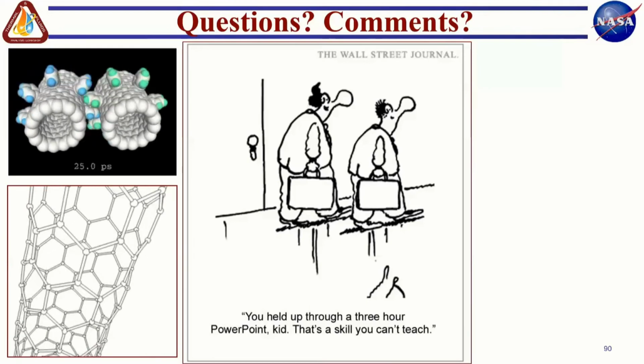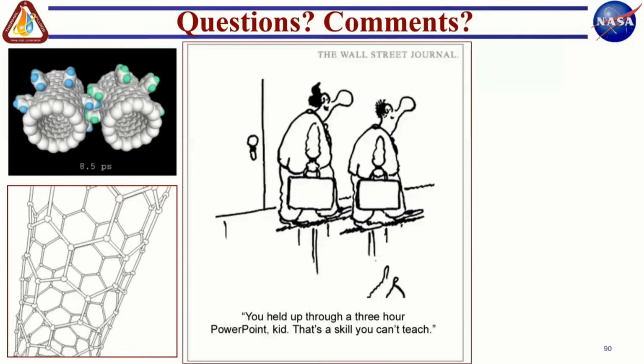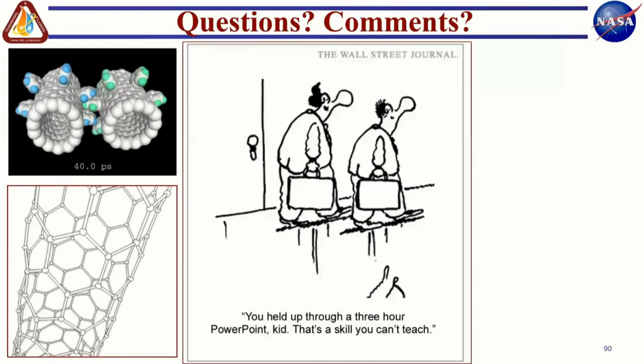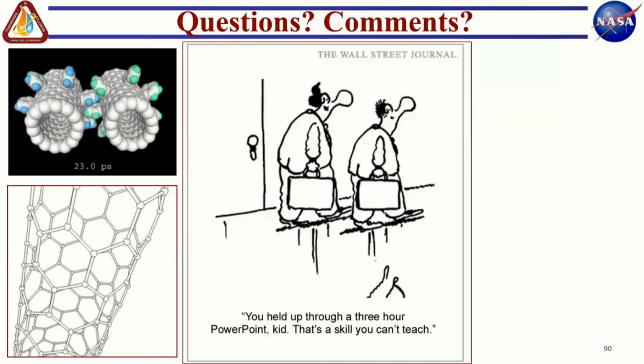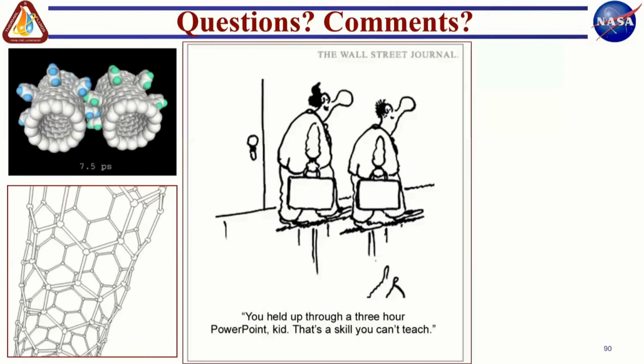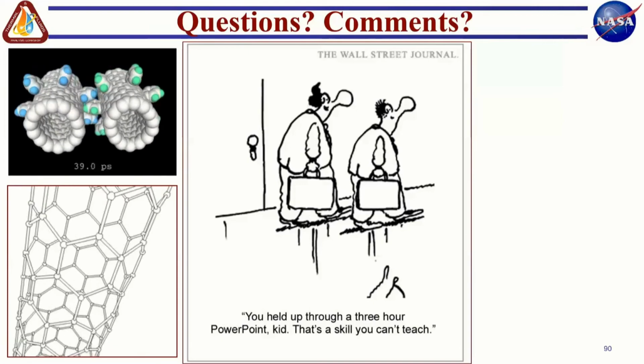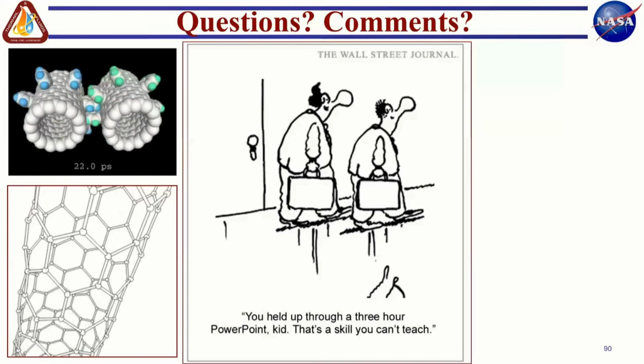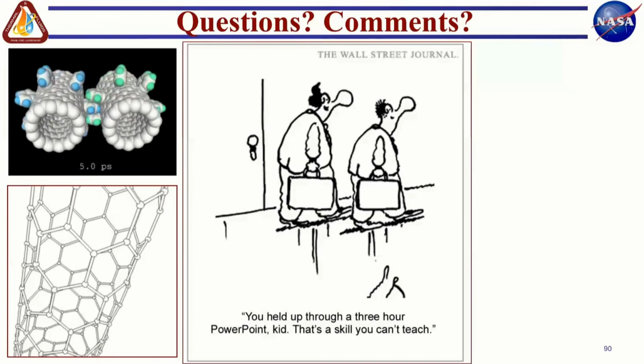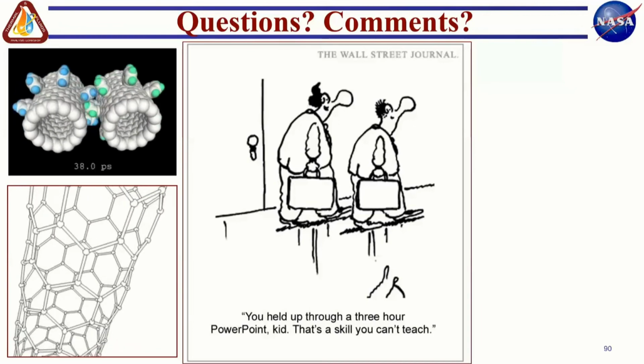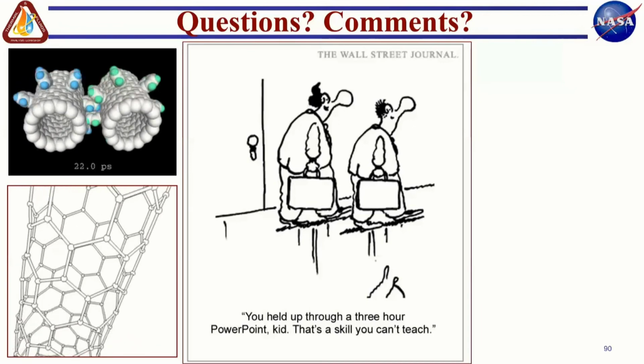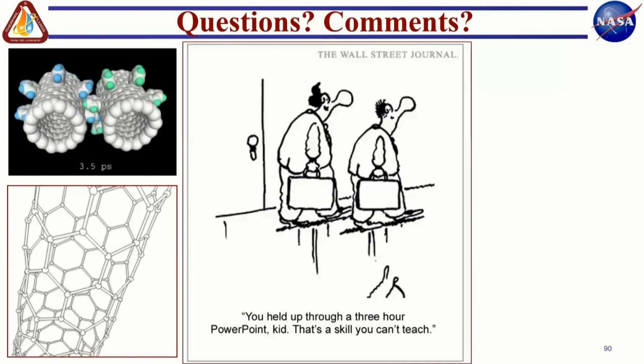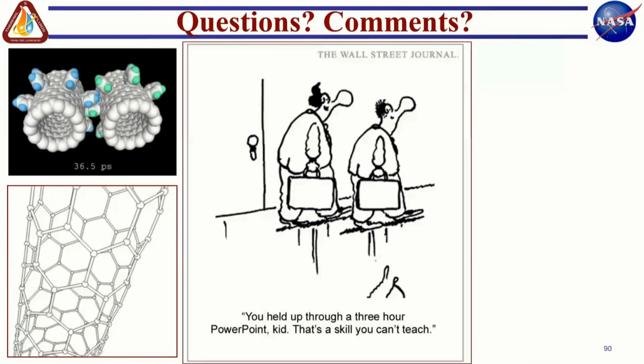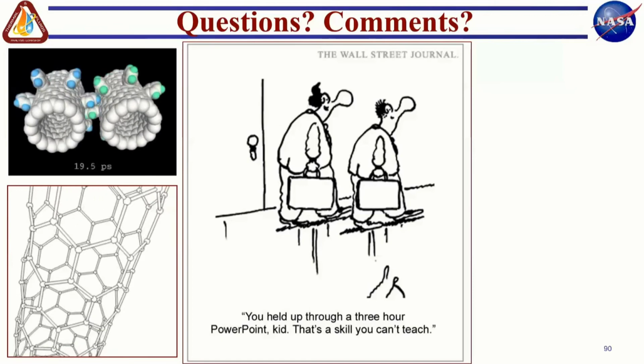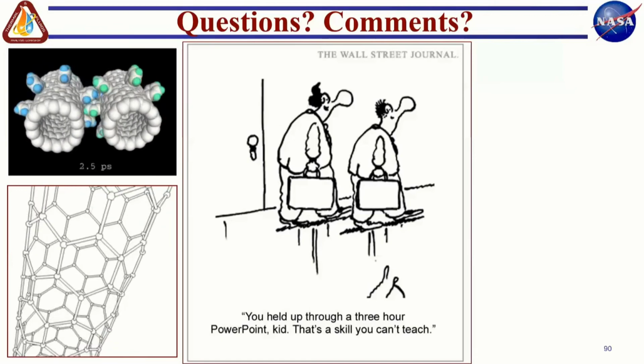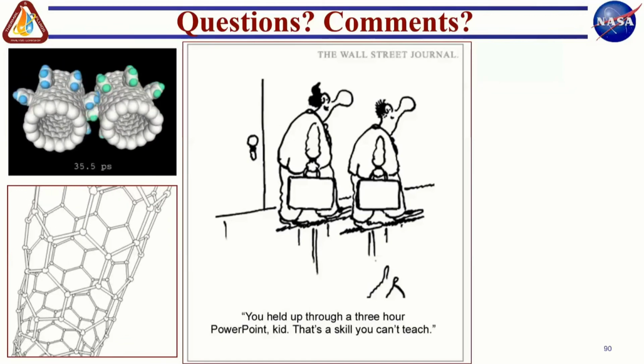bulk. And similarly, if there are other ions, so let's say you have put some sodium chloride as an impurity in the water, the carbon nanotube might like the sodium ions more than the chloride ions. And so you would also set up a concentration gradient for the sodium ions going from the surface of the carbon nanotube to the bulk. So in addition to these hydrogen bonding type of interactions, you can also have ionic interactions depending on the level of purity and the type of impurities you have in your coolant, whether it's water or any other ionic fluid.